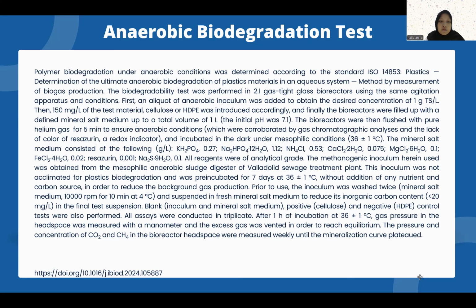First, an aliquot of anaerobic inoculum was added to obtain the desired concentration of 1 gram total solids per liter, then 150 milligrams per liter of the test materials, cellulose or HDPE, were introduced accordingly, and finally the bioreactors were filled up with mineral salt medium up to a total volume of 1 liter. The initial pH was 7.1. The bioreactors were then flushed with pure helium gas for 5 minutes to ensure anaerobic conditions, which were corroborated by gas chromatographic analysis and the lack of color of resazurin, a redox indicator.